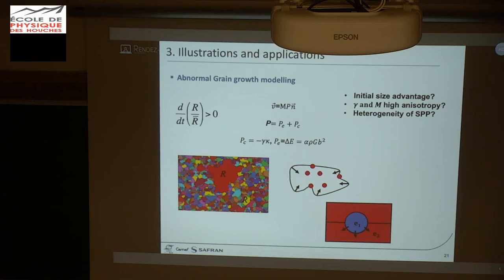You can easily understand that if you have a zone where you don't have second phase particles, you will not have pinning in this zone, and in this zone you will have a larger grain size evolution than in the zone where you have second phase particles. But, for example, Safran came to see us with some experimental data where these two hypotheses were not possible. And the idea was to investigate with numerical, full field simulation, another hypothesis to explain the appearance of abnormal grain growth, which is now well known as critical evolution due to some residual presence of stored energy.